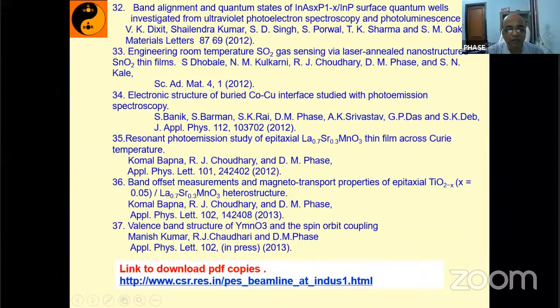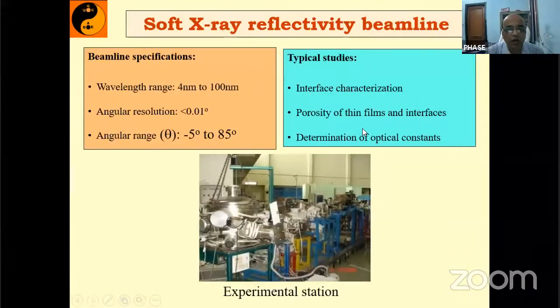And then the other beam lines, as I already told you. One is the soft X-ray reflectivity beam line on Indus 1. Here one can get the reflectivity and one can get the thickness of the thin film. Interface characterization is also possible. Suppose you have a bilayer, trilayer, or multilayer, then interface characterization can be done using this X-ray reflectivity beamline. This is another beamline on Indus 1.